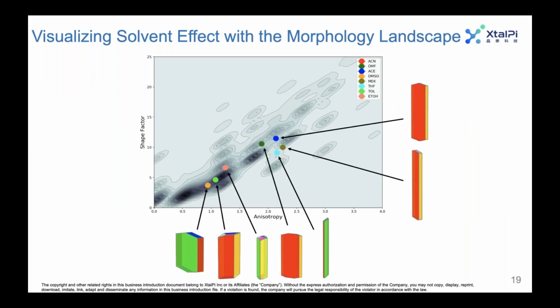And you can put this all together by taking the morphology landscape for this particular molecule, or crystal structure, I should say, and then plotting the predicted morphologies on that morphology landscape. And then we can indicate the solvent system or experimental conditions that yielded that particular morphology. So you can see we have more needle-like predictions in some solvents and more plate-like or even thick plate-like structures in other regions. So this data can all be taken and used to design more experiments. So now you can imagine using some solvent combinations or even exploring some solvent systems with different properties in order to try and push the morphology into even more desirable areas of the morphology landscape.